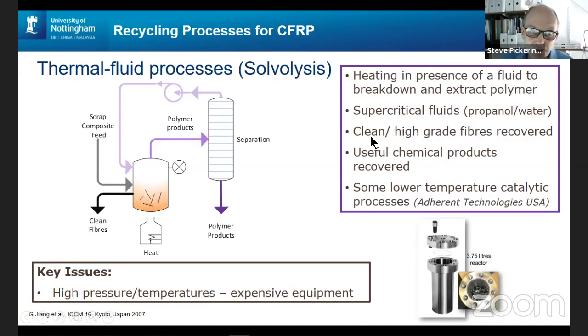You can obtain very clean, very high-grade fibers from these with the solvolysis process, and you can recover some useful chemical products. Although with cross-linked thermosetting resins, they usually don't break down in such a way that you end up with a usable monomer, but you do end up with a feedstock that could go back into a chemical process.